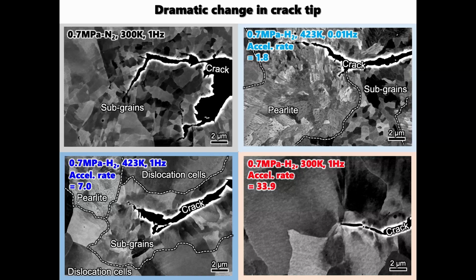But when discussing the difference in the deformation substructures, we should pay attention to this fact that this difference comes from different factors. One is the intrinsic hydrogen dislocation interactions. I mean, the hydrogen segregates around the dislocation cores forming the atmosphere, which work as a strong resistance to dislocation motion.